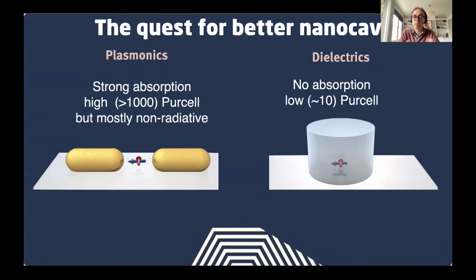So these are high index materials, and our favorite is gallium phosphide, which are designed to confine the light internally by what we call the Mie resonance, which is the interference of the light in the particle. Now, at the beginning, and you see in this slide, the plasmonic was much better, reaching 1,000 enhancement, whereas the dielectric were at the 10th level.